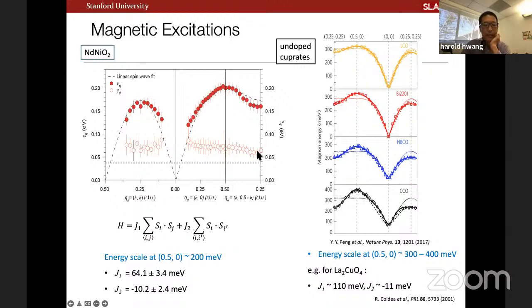The second thing that we see here is that our magnetic excitations are quite broad, right? So in the cuprate case, these are generally resolution limited in terms of a RIXS experiment. In our case, we're quite a bit above our instrument resolution. This is roughly the half width at half maximum, and this dotted line is the experimental resolution. And you can see that they're quite broad. If you dope the system, you can chase the dispersion relation a little bit further down, but it rapidly just damps out, so it's very hard to distinguish experimentally what's going on. So in summary, the magnetic excitation spectrum of the parent compound of the nickelates looks rather similar to the doped cuprate, actually. And we suspect that these electron pockets, for example, are contributing to damping in the system.